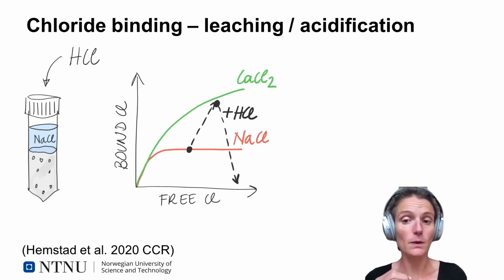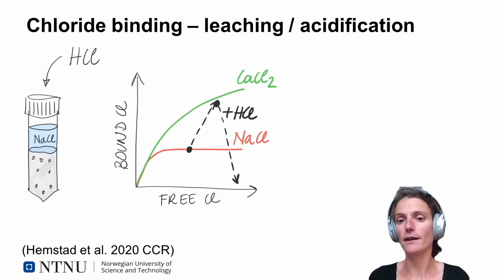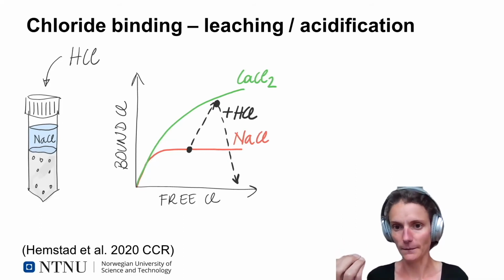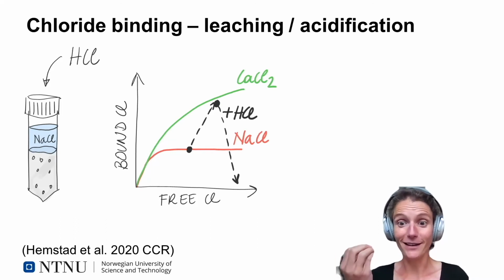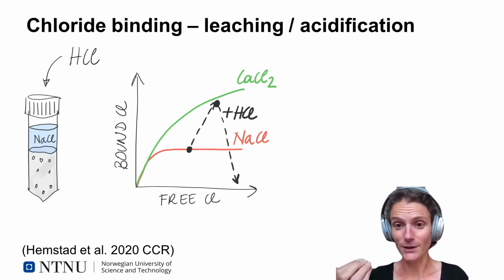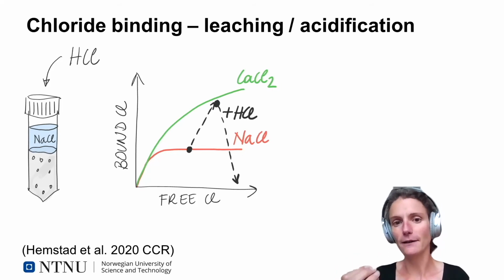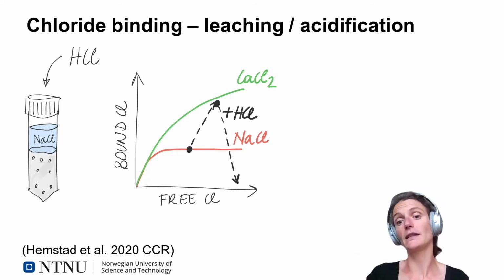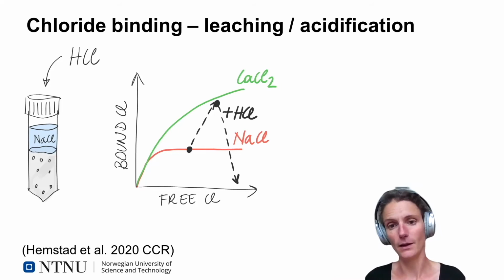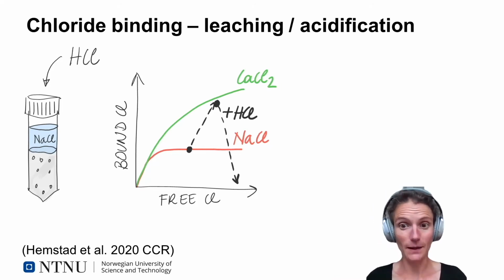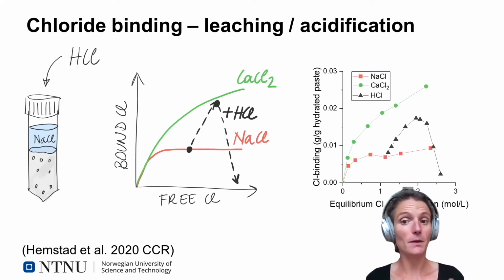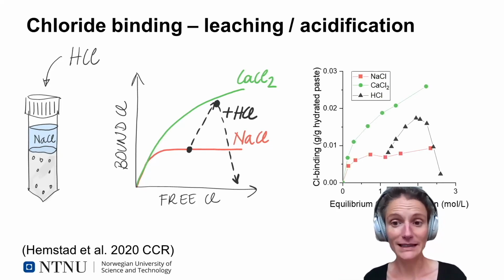And our hypothesis was that as we in that case are decreasing the pH, you would have an increase in chloride binding. So we are adding hydrochloric acid to our system. At a certain point, we will start dissolving chloride binding phases. And then we would expect a drop in the chloride binding. So this was our hypothesis. And then we made the setup. And our experimental results confirmed exactly that.